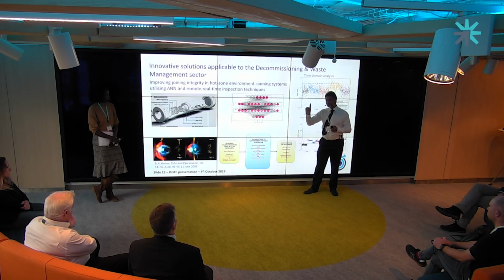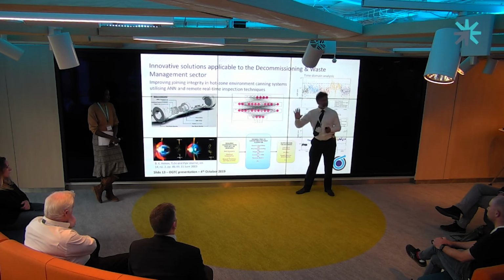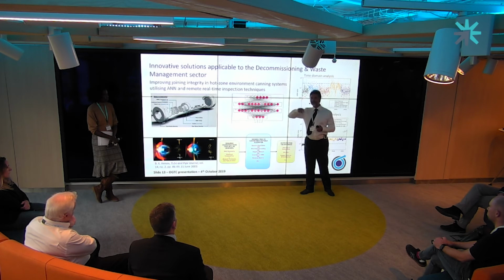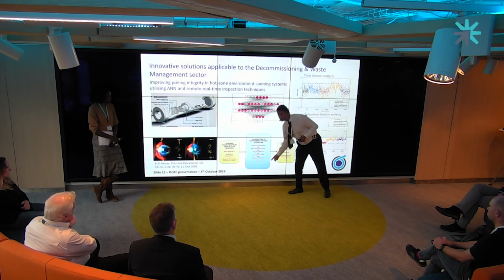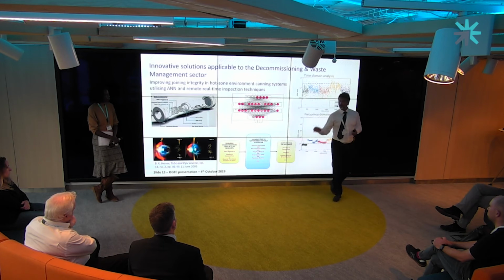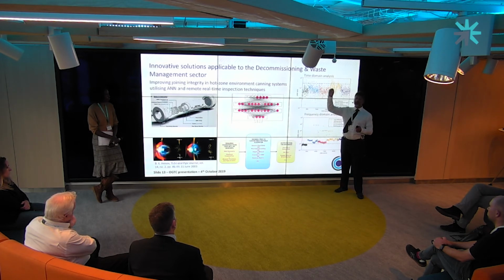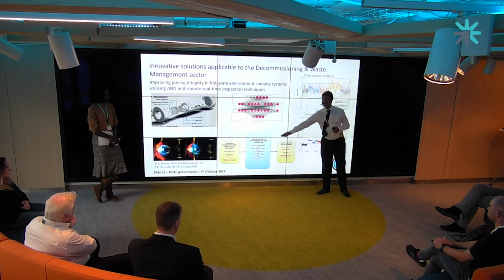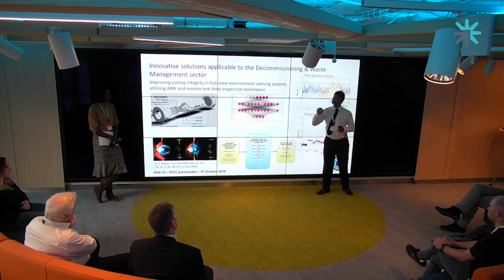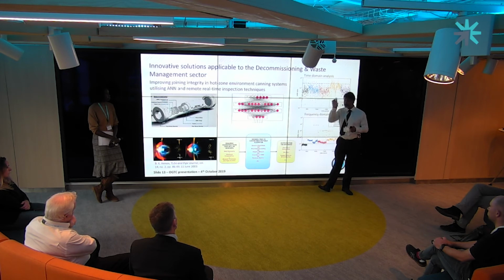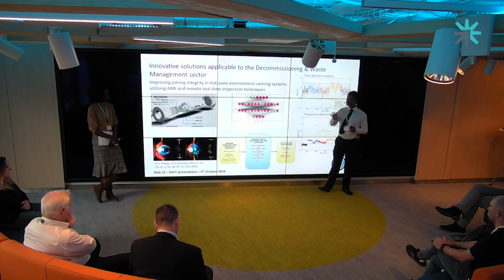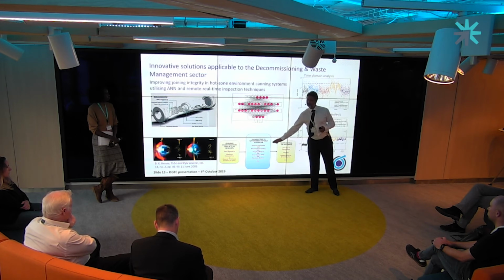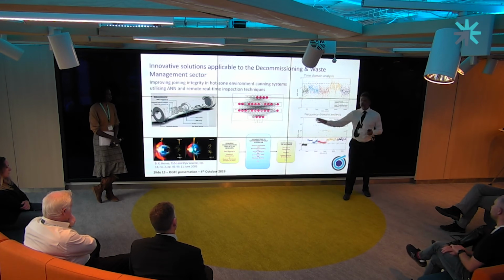So, cutting to the chase, no one algorithm is the panacea to your solutions. You have to test each algorithm. So this black box, which we actually created successfully on a range of materials, it was only from 0.5 millimeter to 2.5 millimeters in stainless steel, we could actually get a weld that would then predict what the stress concentration factor is at the toe, and we can also predict what the austenite ferrite level is from the classic diagrams that you get. So these are the things that I am really passionate about, that we need to start collecting. And big data is one of these things that we talk about as a buzzword, but only when you start analyzing it and creating these machine learning programs will you get anywhere.